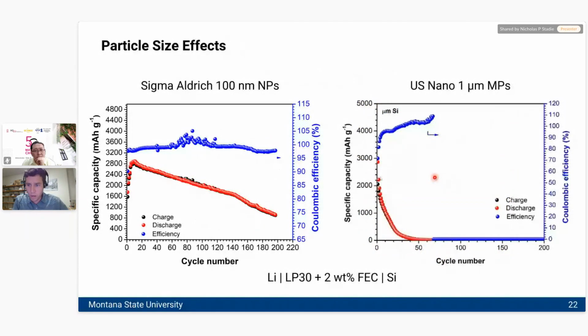So that explains why you have this rapid loss of capacity with cycling as you expand, contract, expand, contract, expand, contract your silicon anode. Those particles are occasionally being lost from electrical contact on your electrode, and they're basically just swimming away. If you lose a particle from electrical contact on your anode, you can no longer lithiate or delithiate it in the next cycle, and that's basically what's understood to be going on here, even in the best case scenario for silicon, happening rapidly in the case of these much larger particles on the side on the right.